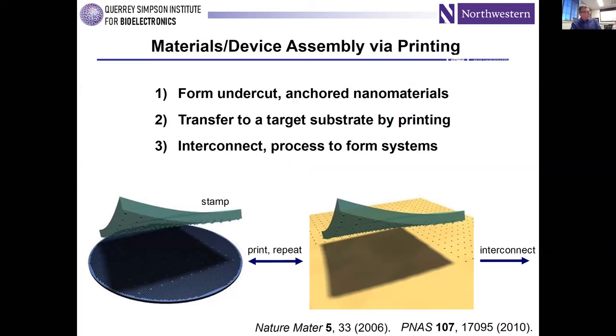And the process involves doing that kind of undercut etching I just described to create what is essentially like an inking pad, where the ink is the semiconductor nanomaterial itself. You take a stamp with raised features of relief on its surface, a very soft material, so it's unable to deliver forces at levels that would crack these materials, but you can bring it into contact with that semiconductor inking pad. The van der Waals forces will be significantly large to maintain adhesion between these semiconductor nanoelements and the surface of the stamp, so that when you peel the stamp back, you basically ink the raised regions of the stamp with the material. And you keep those ribbons tethered to the underlying wafer at anchored points so that they don't just wash off into the etching bath. That's a key thing.